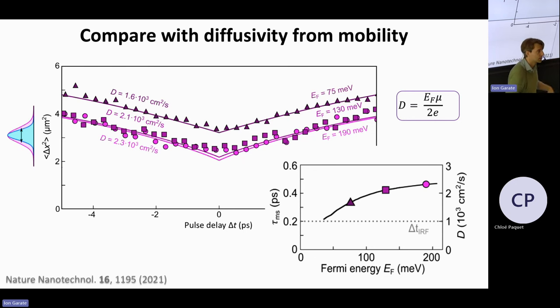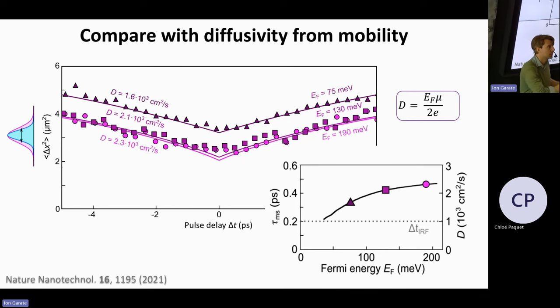And then in the end, it all matched out by being able to really scan through this phase space. Here it's not the Wiedemann-Franz law, it's just the Einstein relation, right? Einstein relation, but you can derive the same results if you solve the Wiedemann-Franz law and the continuity equation under certain assumptions. You get exactly the same result. The EF really here is the N dμ in general, right? Yeah, so for semiconductors there's a factor two difference. Some papers actually use the wrong one because it depends on whether your bands are parabolic or linear. So you have to do the dN dμ, and then you end up with this one.